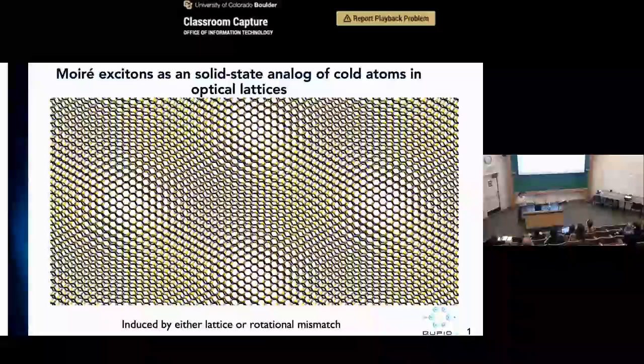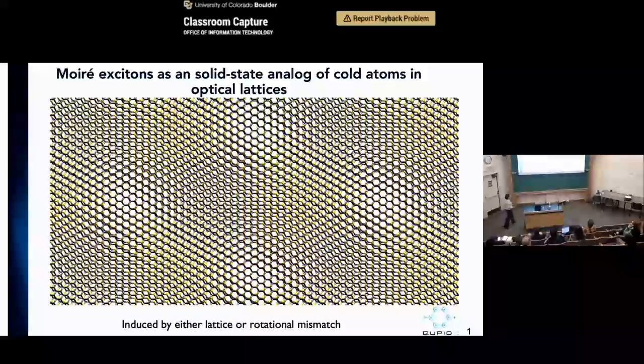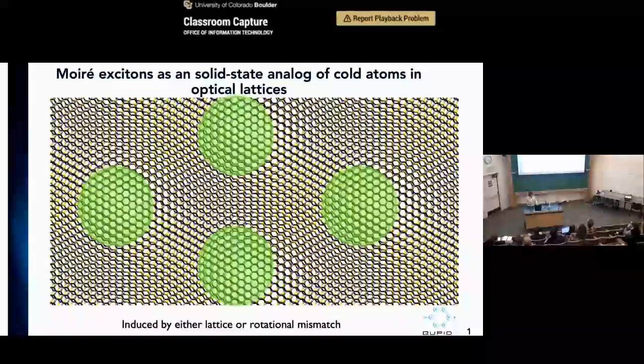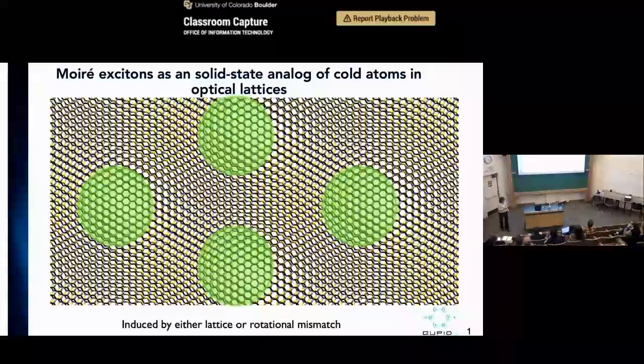So now, how do we get to this strongly interacting case? To do that, we need to engineer a lattice for this exciton so that we can study that correlation. The way we increase the interaction is by using a Moiré superlattice. It's a bilayer system, in this case a single layer tungsten disulfide on top of a single layer tungsten diselenide. Because these two lattices have a 4% mismatch, you essentially create a new superlattice, highlighted by this green dot.